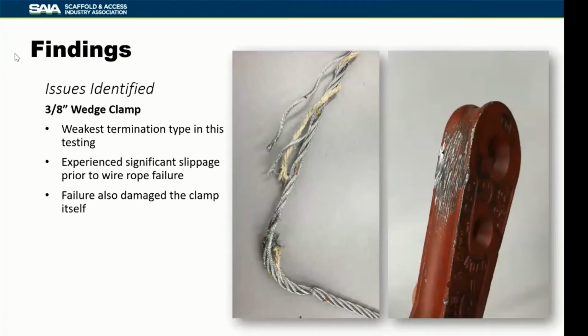So with the 3/8 inch wedge clamp, we did experience significant rope slippage prior to the rope failure. And then after the rope failure, as you saw in the video, the entire wedge became dislodged from its fitting. And in looking at the wedge after the test, you can see the damage to the wedge itself by the rope sliding through it under pressure as it was.